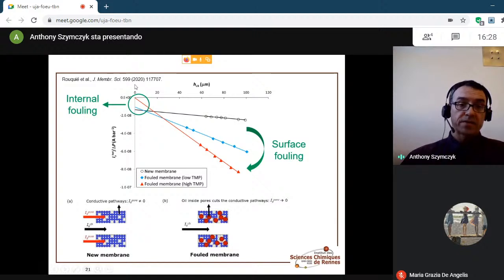The disappearance of the electrokinetic leakage is explained by the fact that when the oil penetrates inside the porous membrane matrix, then it cuts the conduction pathways in the membrane matrix, in the membrane porosity, thus preventing the circulation of the leakage current inside the membrane.